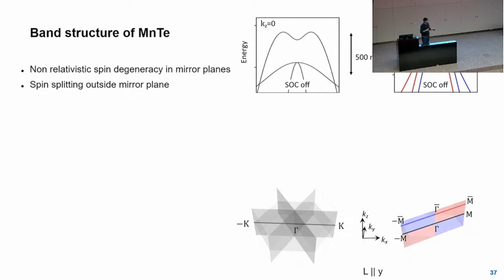And now, of course, we can do these band structure calculations. And there is one detail, but an important detail, which I kind of hid from you. All of what I told you is exactly true only in the limit when we ignore that the spin actually interacts with its environment. This means we say we don't have spin-orbit coupling. In the case we don't have spin-orbit coupling, all of what I said before is exactly true, and spin-orbit coupling is a small correction to what I've said before. So, if we now do these calculations without this interaction, then we get exactly what symmetry tells us. Symmetry told us there are certain planes where we still have degeneracy in this system, and those are where the spin up and the spin down have the same dispersion. So that's the boring plane. But if we go into a different part of this Brillouin zone, and calculate the dispersion, then we get these nicely and widely split fully spin polarized bands.